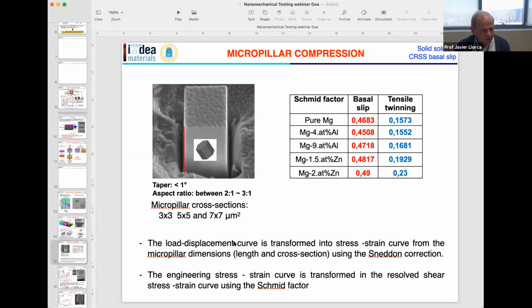The load displacement curves from the micropillar compression were transformed into stress strain curves from the micropillar dimensions using the Sneddon correction to take into account the deformation of the bulk of the material.